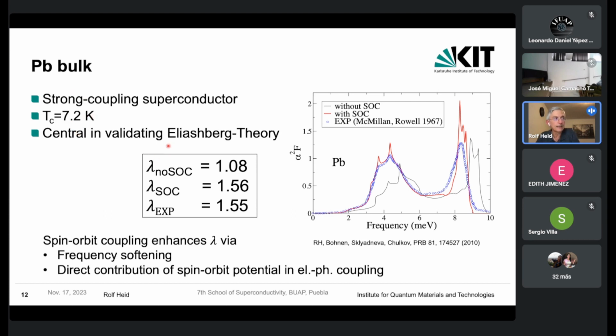but lead has been actually central in validating the Eliashberg theory. Namely, already in the 60s, one was able to extract experimentally from tunneling experiments this spectral function, the Eliashberg function alpha squared F, which is here shown from one of the famous experiments by McMillan and Rowell, shown here by these blue dots, blue circles. And this is now compared with some calculations done more recently for lead, using the spin-orbit interaction included in the full formalism. And this is given here by the red curve, which shows a very nice agreement with this experimental